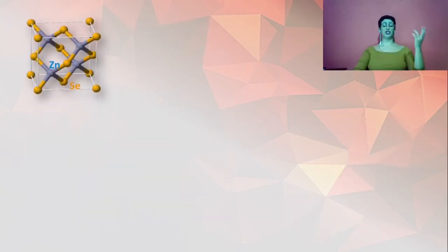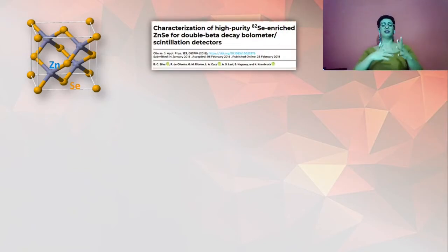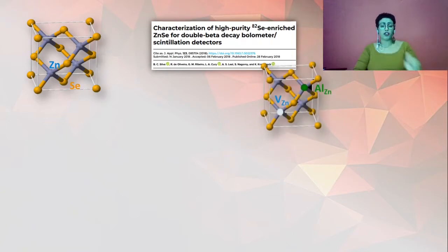Zinc selenide is a II-VI semiconductor with a direct band gap of 2.7 electronvolts and grows in a face-centered cubic structure. In a previous work, we investigated luminescent zinc selenide crystals enriched with the selenium isotope grown by the Bridgman technique. By EPR measurements, we observed the presence of some impurities at very low concentrations, and we identified by photo-EPR zinc vacancies paired with shallow substitutional donor impurities of aluminium as the dominant radiative recombination center responsible for the yellowish-red luminescence typical of zinc selenide.